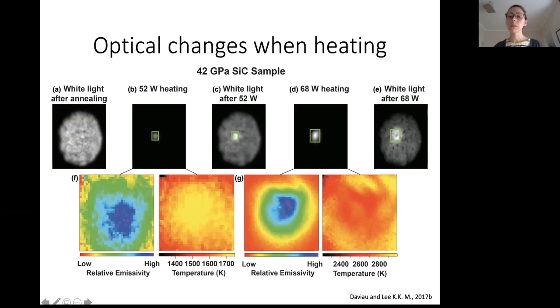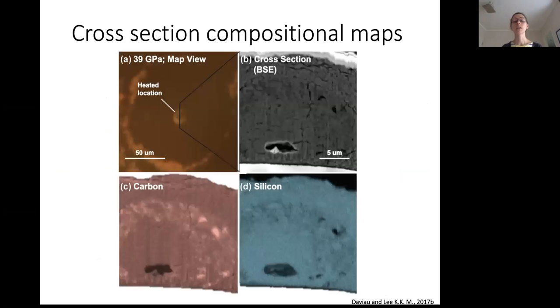So what seems to be happening is that whatever this breakup, this phase change in silicon carbide's melting behavior, is causing optical changes in the sample, which then begin to alias the light, so that you start to see uncorrelated temperature and emissivity maps. And so if we go through a whole bunch of samples and look at what temperatures this happens, we can begin to find where this phase change may be occurring.